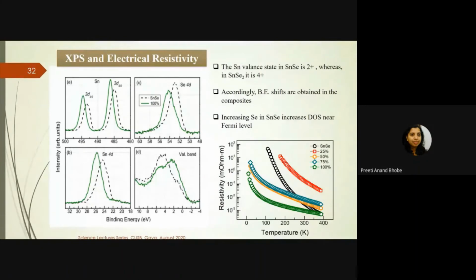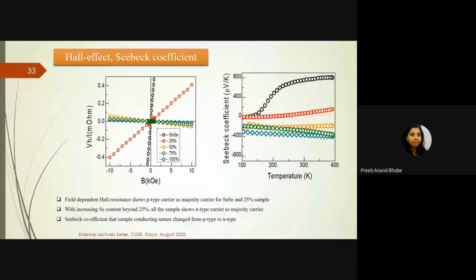So the density of states at the Fermi level increases with the presence of the secondary phase. This fits in very well with our Seebeck coefficient values, as well as the Hall effect carrier concentration that one gets from the Hall effect. And what one finds is that yes, the secondary phase is playing a role, because our Seebeck coefficient, which was a p-type material and hence positive, with the increase in the SnSe2 phase is going towards the negative value with n-type conduction.